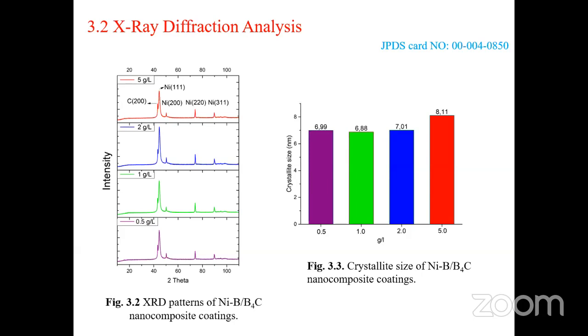The peak intensity and width are directly related to microstructure. According to the Debye-Scherrer formula, the lowest grain size was measured with the addition of 1 gram per liter boron carbide, while the highest grain size was measured with the addition of 5 gram per liter boron carbide. With the addition of 1 gram per liter boron carbide, the second phase causes grain refinement by preventing grain growth and creating new nucleation zones. The particles added to the bath composition at 5 gram per liter started to agglomerate in some areas. Thus, the grain refining effect could not fulfill its grain refining function completely.